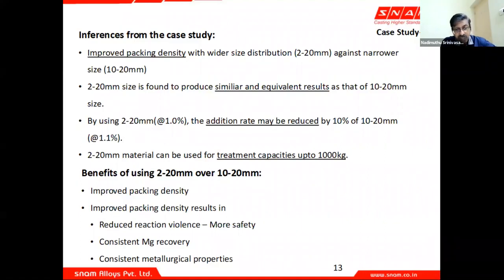And 2 to 20 can be used for treatment ladle capacities up to 1000 kg. I hope most of the foundries use the 1000 kg ladle, and for such foundries it is very good. And foundries which have a higher capacity, they can use a 2 to 25 mm treatment size. The benefits, so once again, to just summarize: improved packing density, which results in a reduced reaction violence, which means more safety. When there is some worker holding the treatment ladle and standing beside, there are no flares, violence or sparks coming out, so it is much safer for the person. You have a very consistent magnesium recovery, which is seen from the residual magnesium and from the consistent metallurgical properties.